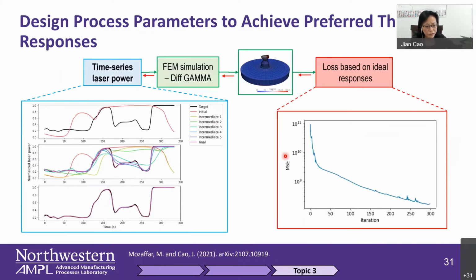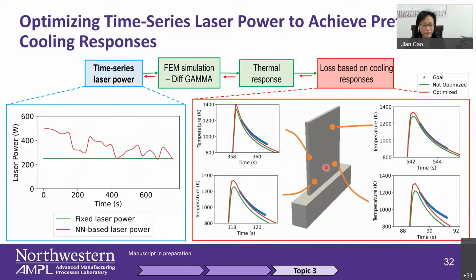So first, what we did was try to see how we can control the entire thermal history rather than just the melt pool. So when you look at this, we did a test run to see whether it could converge, right? The story is that yes, you can converge. And then we went back to our single wall, and said let's control the entire cooling time as well from different points.